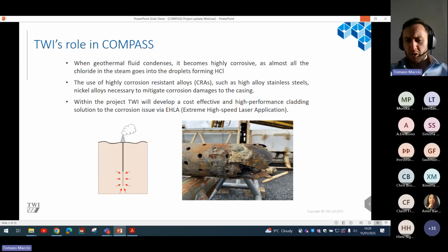geothermal well. Now, I don't believe this was in for a long period of time, and I believe a few hundred meters of the pipe is missing from the bottom. So the corrosion was that severe that it resulted in either a complete break or the complete corrosion of a large piece of metal. So TWI's role within the project was to use high corrosion resistant alloys, or CRAs, such as stainless steel and nickel superalloys, to create an effective corrosion resistant layer on top of the mild steel substrates that are used in the oil and gas industry and very widely used in geothermal environments.